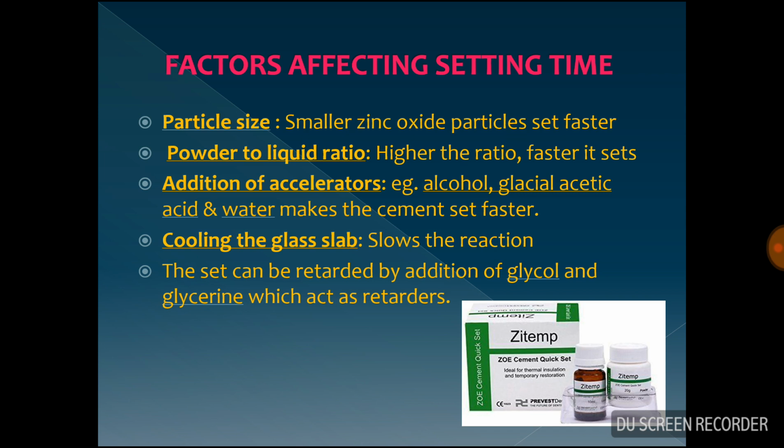Cooling the glass slab: cooling the glass slab slows down the reaction. The set can be retarded by the addition of glycol and glycerin, which act as retarders.